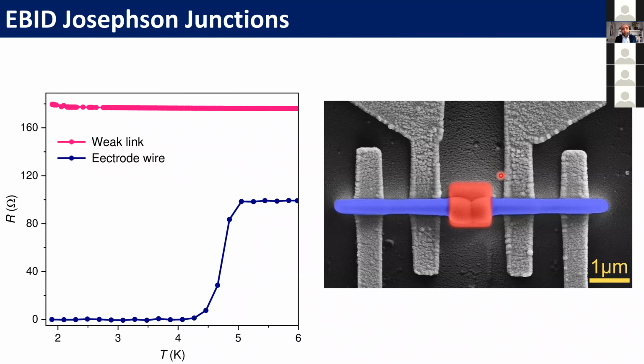Let's be clear, this is not part of the junction. These are just normal metal wires that we use for making connections to our Josephson junction. Apart from that, everything is done in the scanning electron microscope. And as I said, this is simply by changing the scanning speed, or how much you linger at each point while you're scanning the electron beam during EBID. We can get both superconducting and non-superconducting, but metallic components. And that's how we make the junctions.